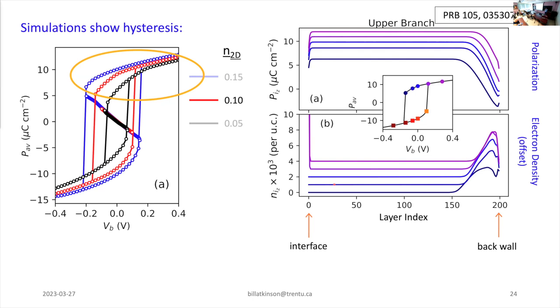I see. So the transition doesn't really have anything to do with loading this other band? You're talking about the hysteresis curve in the inset, color matched to the curves in the bottom, right? Yeah. And the polarization has a sudden jump from the top branch down to the bottom branch. That's just the point at which the states of the interface become lower in energy than the states of the back wall. In fact, that's not true. The states of the interface are lower in energy throughout much of this branch. These are just metastable. Okay, thanks.